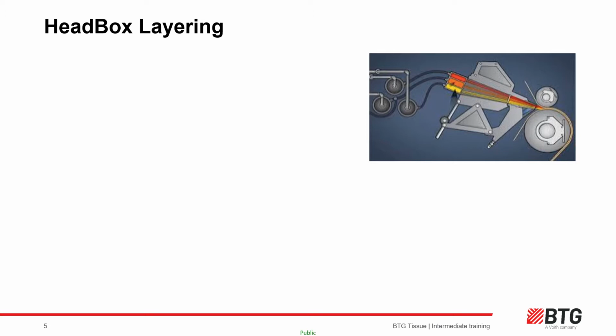This is a triple layer headbox represented by the red, orange and yellow layers. Usually short fibre would be diverted to the Yankee layer and the longer fibre or perhaps cheaper fibres to the middle layer or felt layer, sometimes called the non-Yankee or hood layer. Lamination also adds intrinsic strength to the sheet. During converting, 2 or 3 sheets are often wound together with Yankee layers on the outside surfaces for hand feel.